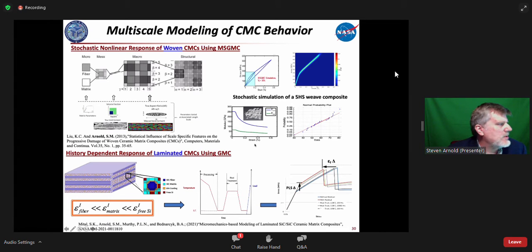Here's another example of multiscale modeling of CMC behavior. Here we're showing two different types of problem. The first is a woven system. The second is a laminate. But we've done a significant amount of investigations of the stochastic nonlinear response of woven composites, where we've varied a variety of the different features at the local or lower length scales, and observed how they influence the behavior at the structural or global composite level. And here we're just showing some illustrations where the nice thing is you can see the composite would go up, have failure, and then when you unload, you actually come back at a different stiffness, as one would expect, due to the fact that damage is present.